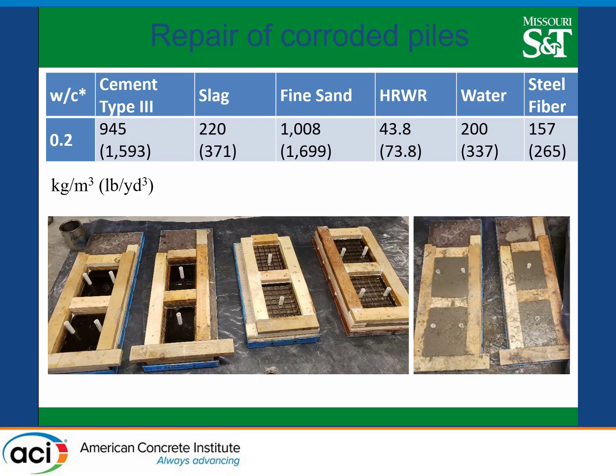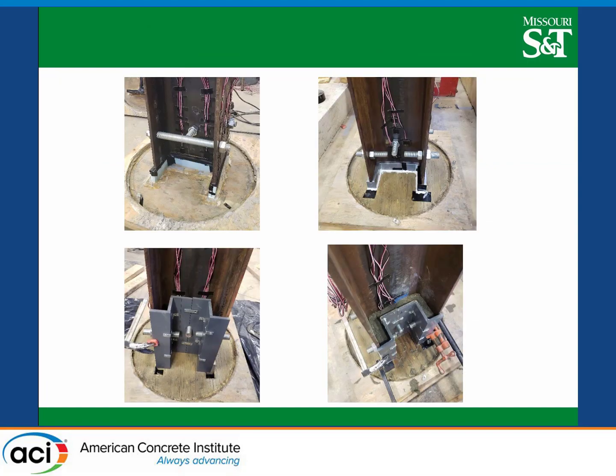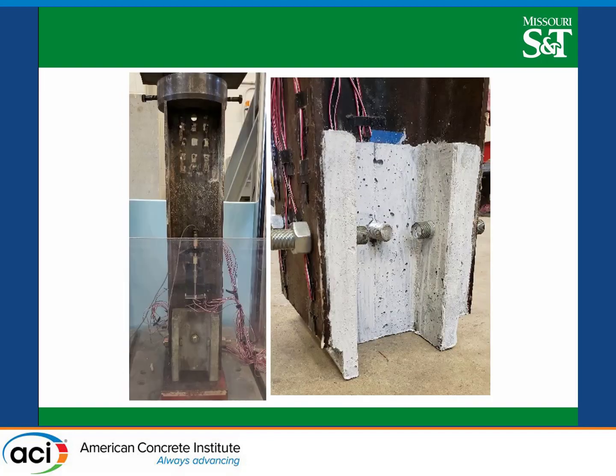So we have a first layer, install the carbon fiber, another layer of concrete, and then a layer of carbon fiber, and then concrete. The total for these 2 layers of carbon fiber, the thickness was about 2¼ inches. We have a cover of 0.75 inch, 1.5, and then 0.75 inch of carbon fiber. And we also looked at cast in place, where we would like to evaluate how much you get from the cohesion and how much you can transfer through the steel studs. So we have those cast in place just to help us evaluate the cohesion component. And we have those over here with the precast.